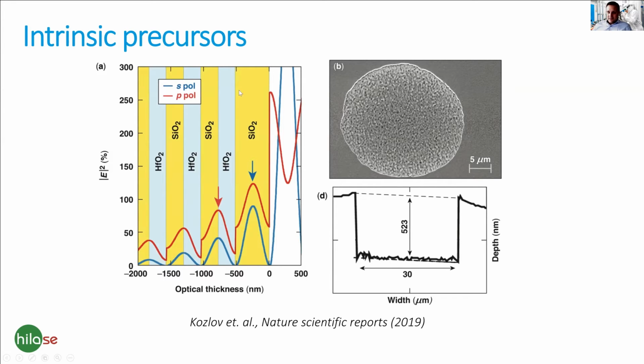So first, you can see, as I mentioned before, that the behavior is different for different polarization. Usually, what is commonly understood is that p polarization is, from the damage threshold point of view, worse than the s polarization because the E field enhancement on the interface of two different media with different effective indices is higher.